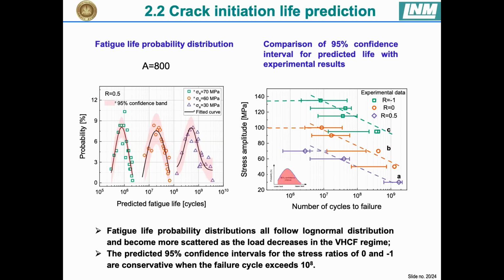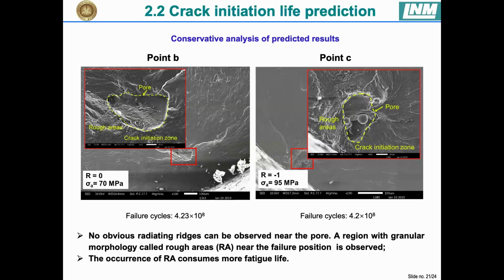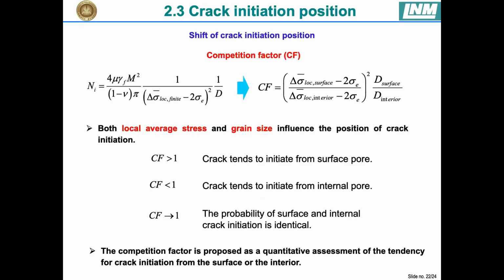For the corresponding results of point B and point C, the corresponding fracture surfaces are observed. It can be found that no obvious radiating ridges can be observed, and the region with granular morphology, called the rough area, is observed, which means the occurrence of the rough area can consume more fatigue life. And then, about the shift of crack initiation from the initial position, the competition factor called CF is proposed as a quantitative assessment of the tendency of crack initiation from the surface or the interior by considering the influence of the average local stress and the grain size.